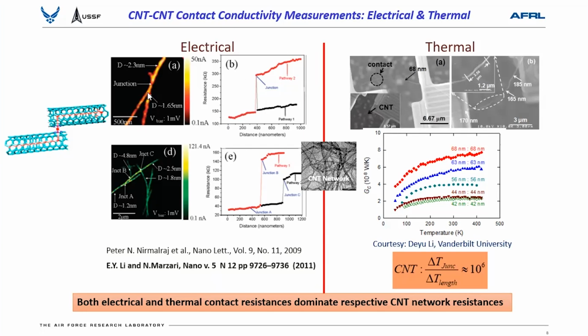If you follow the nanotube across the junction, same nanotube, there's not much of a change. Whereas if you jump from one nanotube to the other nanotube through the junction, there's a big resistance. This interface resistance is quite high unless you tailor this interface properly with nanoscale material design. The same is true for electrical, and the same is the case for thermal, and that interface resistance is very high as compared to the individual carbon nanotube resistance.